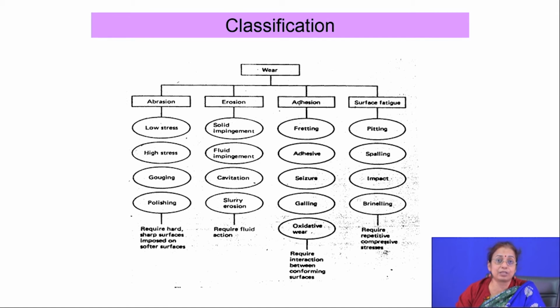You can have a simulated condition by applying lubricants, by increasing the temperature, or by applying different liquids in between, so that the environment is similar to that used in actual conditions. Then you have a relative movement between the two surfaces. The movement may be sliding, reciprocating, or fretting. You can control all these movements externally with the help of software, and you can vary the load and the time.